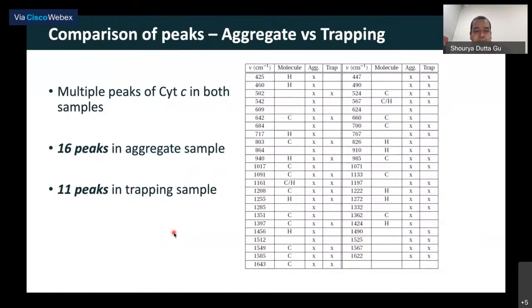And then, of course, you can compare the peaks that you have. For example, here, these are the different Raman peaks that we see for the case of the aggregate and the trap. And then we see that most of them match. And then we are able to conclude that you have cytochrome C in both the samples. However, for the trapped particle case, we have very few molecules from which we are getting the signal, right?